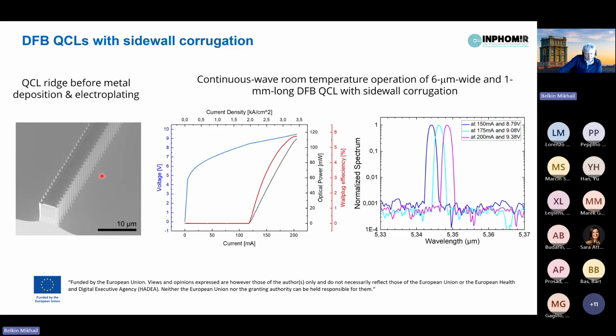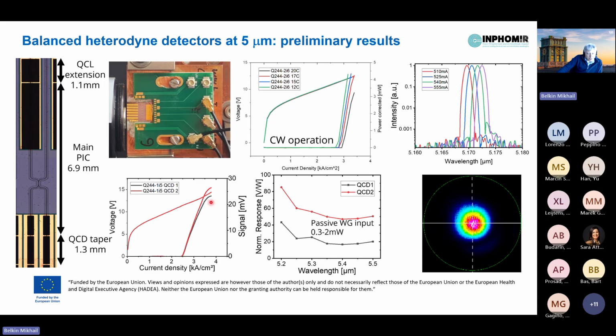Surface recombination plays no role in inter-subband devices, and that allows us to build these DFB lasers in a single etch. And this is some of the performance of these DFB lasers for operation at 5.3 microns, roughly, grown separately, and you can see that the performance is actually very high by QCL laser standards. And so recently we implemented the first photonic integrated circuits for 5 microns based on balanced heterodyne detection.